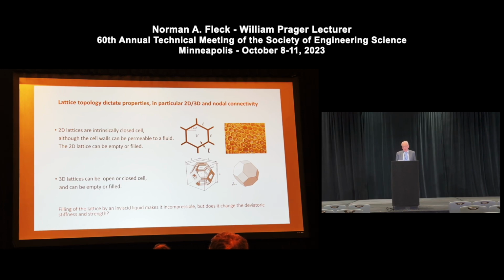What I'll show in my talk is the result that if you constrain the volume inside the hexagonal honeycomb, you've added a constraint equation, and so it's in a sense behaving as a structure that's now got a nodal connectivity of 4. This constraint of the volume means that it's right at the transition between a bending structure and a stretching structure, and we'll see that. So in some of its response, it deforms in a much stiffer way when it's filled with a liquid than when it's empty. That's not true for the 3-dimensional world, where the nodal connectivity is significantly less than 6, and so the imposition of a constant volume constraint does not change this fundamental result that the structure still wants to bend. But I'll come on to that.